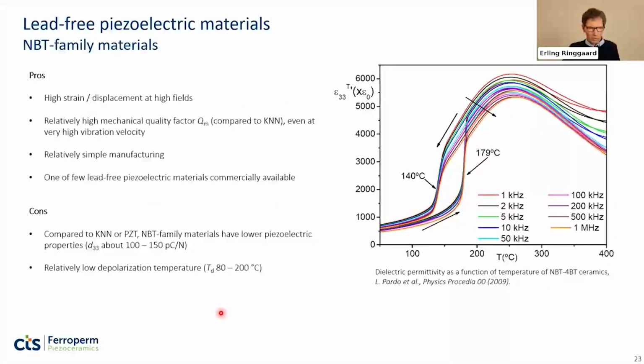Also, very briefly about the NBT-BT materials, you see here one example with a 4% barium titanate, where you see this concept of a relaxor-based material, and it actually shows some relaxor behavior as seen here, and there's also quite low depoling temperature, as you see. But still a very promising material and not as difficult to make as KNN.